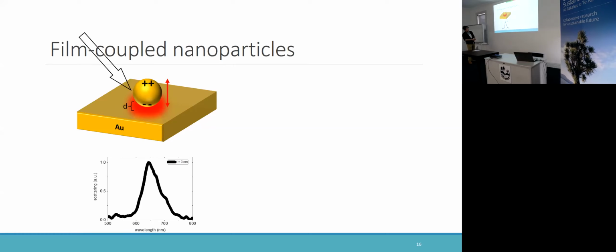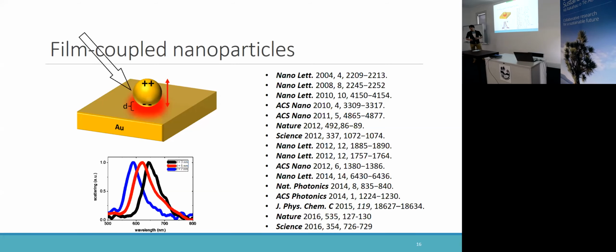And here we can see the absorption spectrum. Here's a resonance. When we change the distance between the nanoparticle and the gold mirror, the gap spacing, for example from 3 to 7 nanometers, we can see the blue shift of the resonance. This structure is very popular in nanophotonics because it has very good light absorption ability. It can concentrate incident light between the nanoparticle and the mirror, and so we have lots of applications.